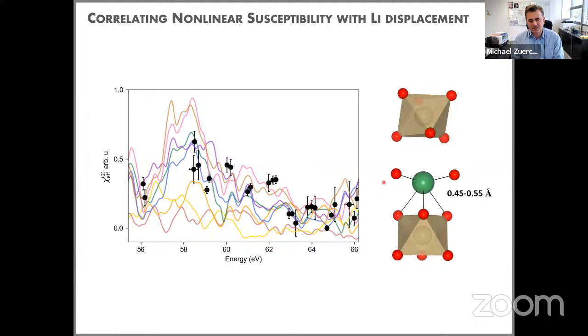But as one of the first works where we really had these highly spectrally resolved spectra, we are still quite happy with the results, since we can first of all replicate the general features: far away from the edge we have basically almost no second harmonic, and then we see these several humps coming from different conduction band states in lithium, and especially around the lithium K-edge, we get a maximizing of the second harmonic response. And indeed, our measurement, these data points in comparison to the theory, allow us to clamp the actual observed displacement of lithium in the system to somewhere between 0.45 and 0.55 angstroms.